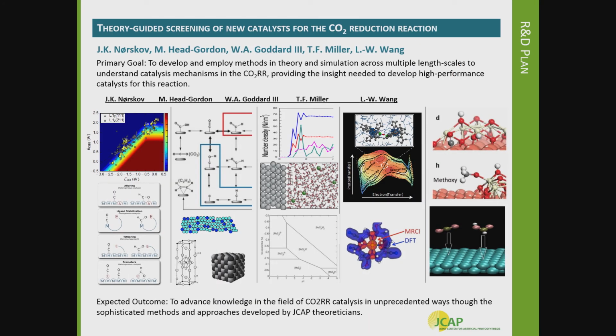And so to address this, JCAP has significantly expanded its range of theoretical efforts, including first principles theory of both the thermodynamic and kinetic landscapes, highly resolved theory of excited states, and also theory of the landscape that includes a detailed treatment of electrolytes, the solid electrolyte interface, and functional components on the CO2 reduction cathode.